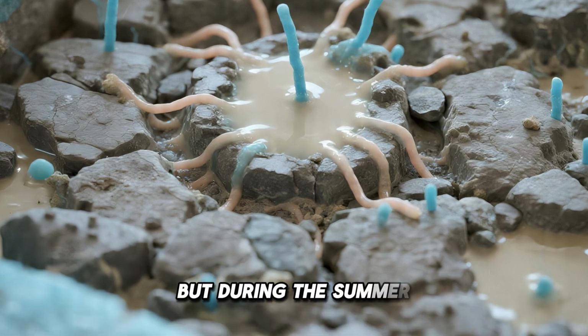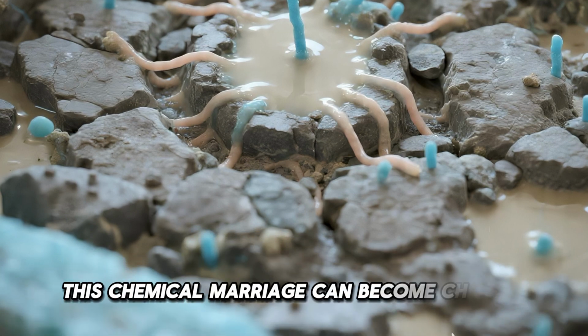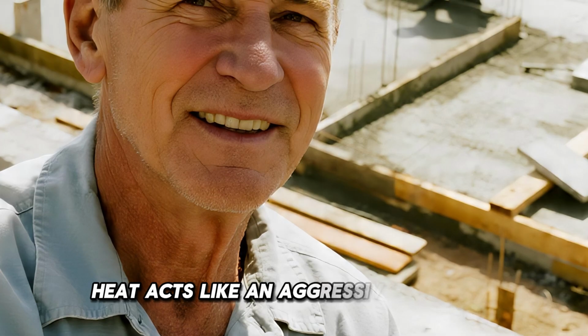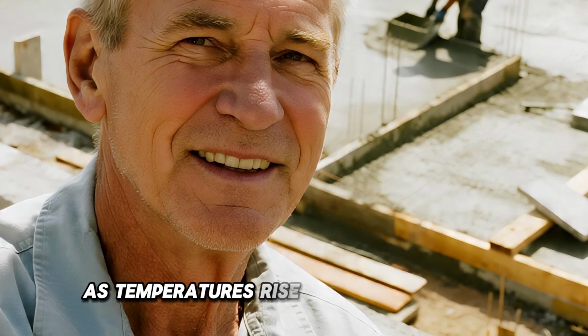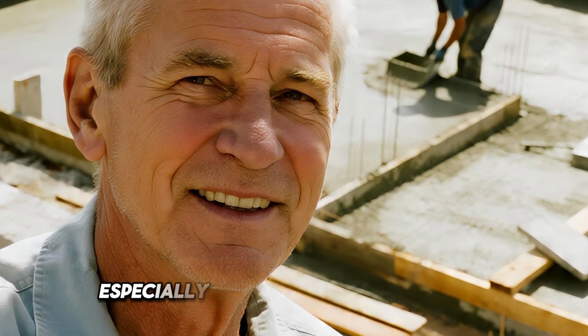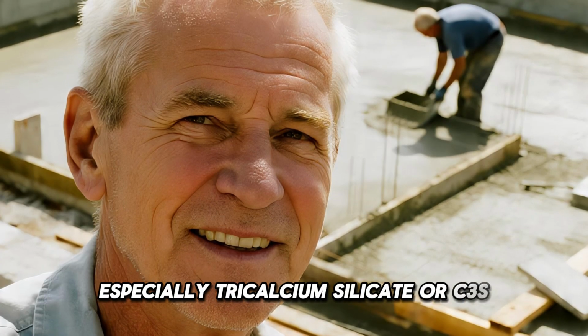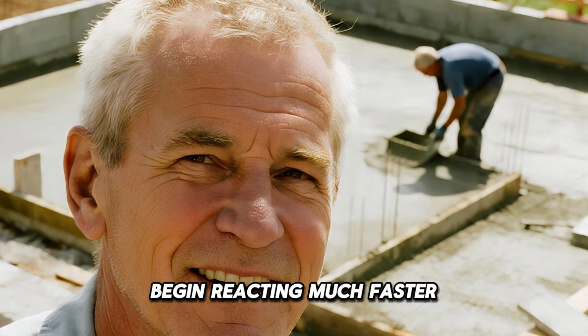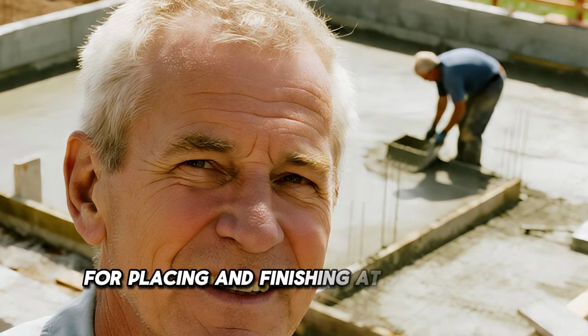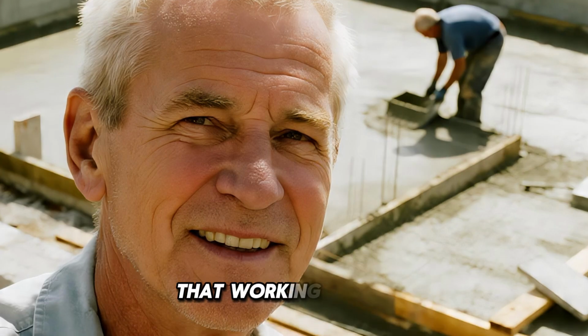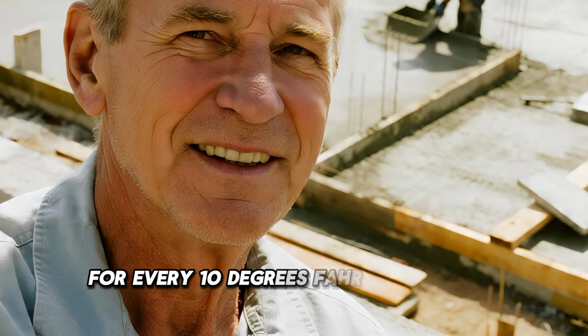But during the summer, this chemical marriage can become chaotic. Heat acts like an aggressive catalyst. As temperatures rise, cement compounds, especially tricalcium silicate or C3S, begin reacting much faster. At around 70 degrees Fahrenheit, concrete may give you a comfortable 4-hour window for placing and finishing. At 90 degrees Fahrenheit, that working window can collapse to roughly 2.5 hours. For every 10 degrees Fahrenheit rise in temperature, setting time can decrease by approximately 30%.